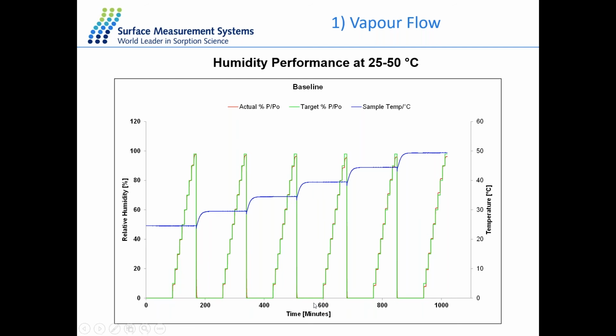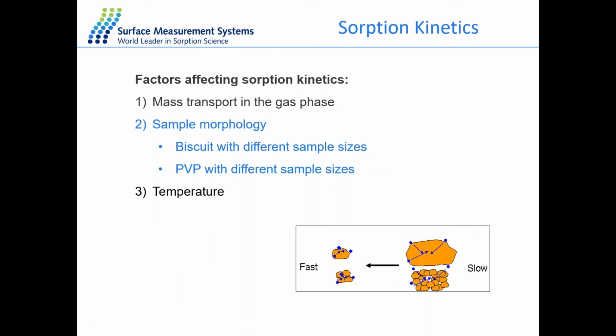And the second factor that will affect the sorption kinetics is the sample morphology. And this is primarily a function of the total sample mass, as well as the average particle size that will affect the moisture transmission or the moisture diffusion into the sample. And this will lead to different time for the equilibrium. And here we have 2 examples. One is with the biscuit sample and the other with the polymer sample.